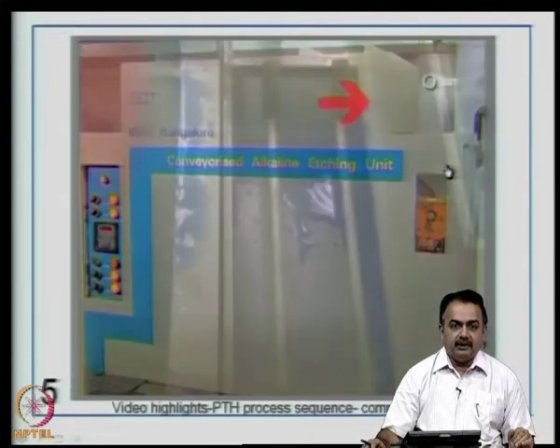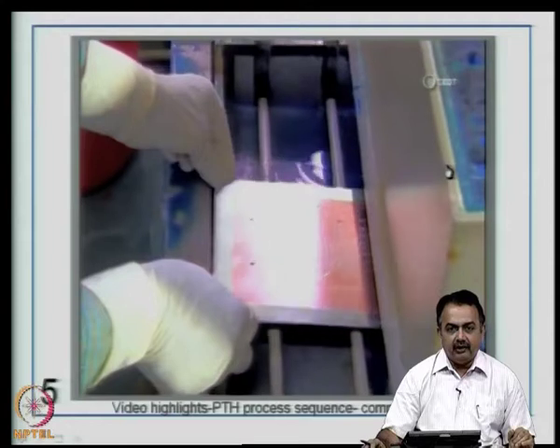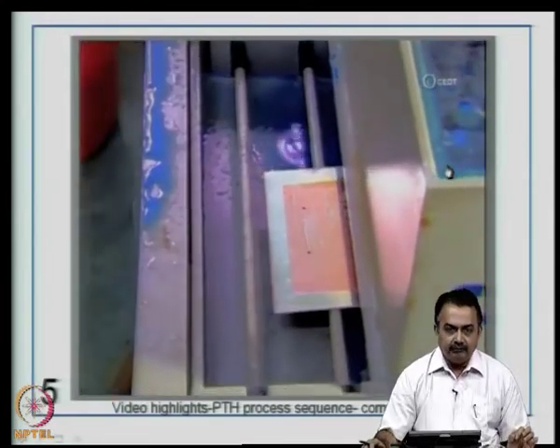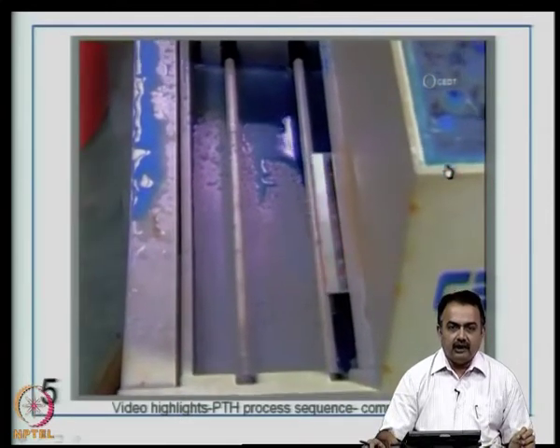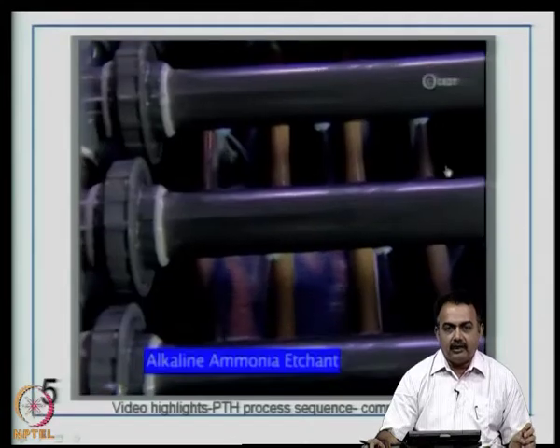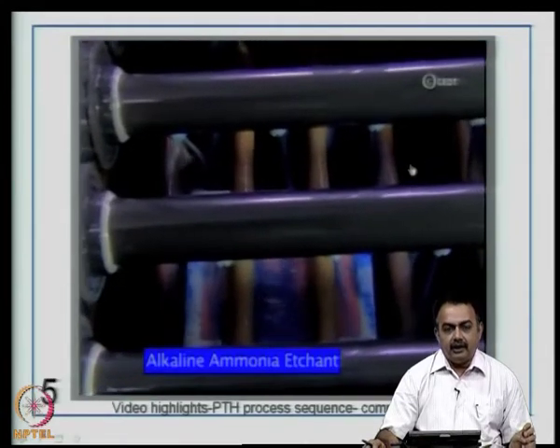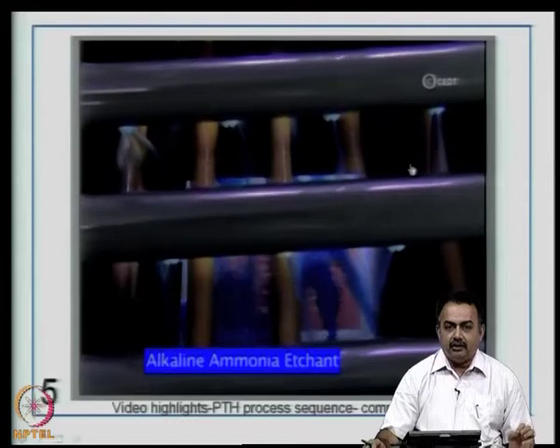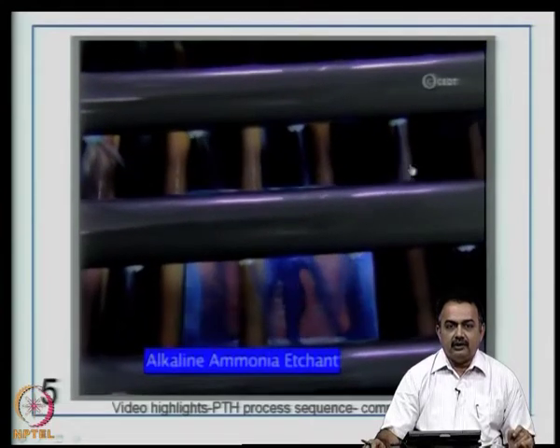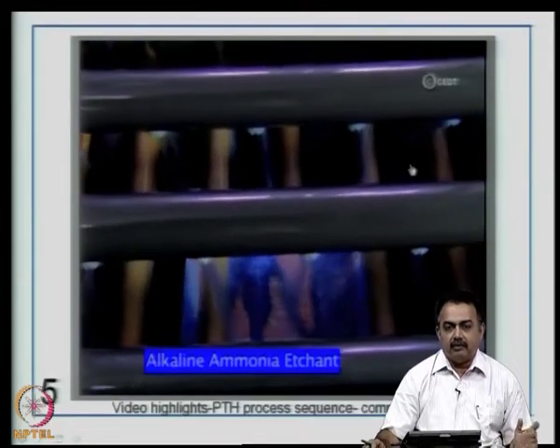So, the next step is basically in this case conveyorized alkaline etching using alkaline ammonia. We have seen earlier the different types of etchants. Alkaline ammonia basically contains ammonium hydroxide, ammonium chloride and liquor ammonia, in addition to copper as a catalyst to start with. You can see that there are spray nozzles from the top as well as from the bottom going through a conveyorized machine, and you can see here there is a water rinse at the end of the conveyorized line.